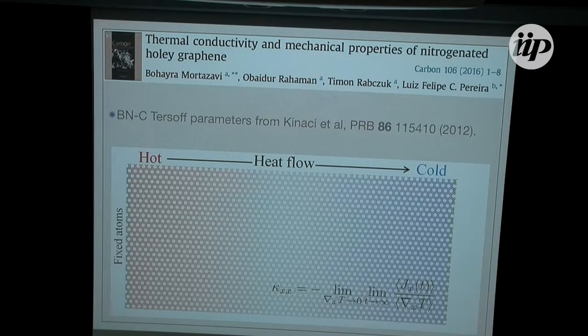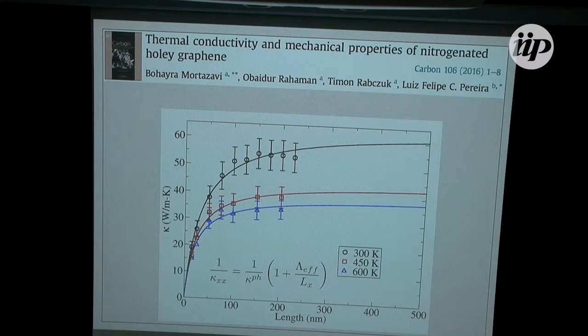And then we set up hot here, cold here. We calculate the thermoconductivity as a function of the system length for different temperatures. We fit with this expression from which we extract not only the intrinsic thermoconductivity of the material, but this effective phonon mean free path. Now, this is not the mean free path of each phonon mode. Each phonon mode has its own mean free path, but this is an average of them all.